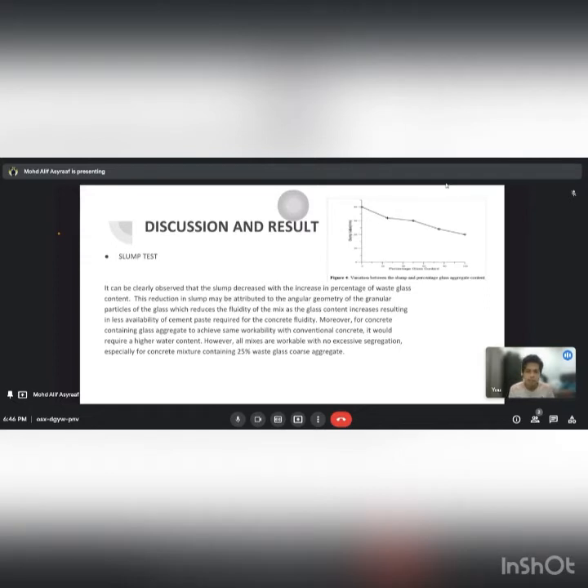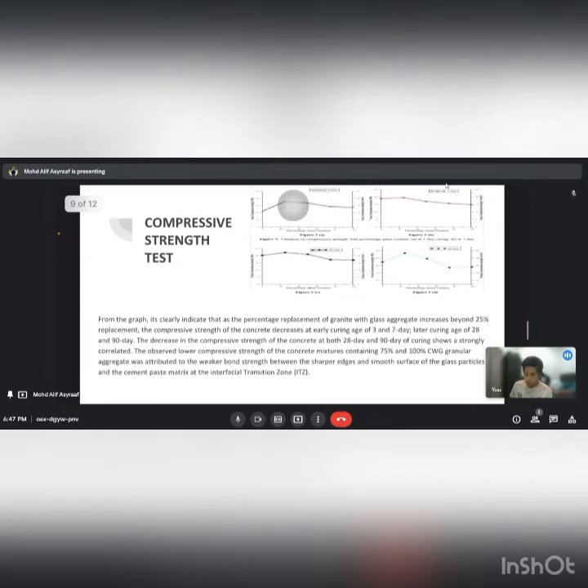So for the discussion and the results, for the slump test, it can be clearly observed that the slump decreased with the increase in the percentage of waste glass, as in the graph above. This reduction in slump may be attributed to the angular geometry of the granular glass particles, which reduces the fluidity of the mix as the glass content increases, resulting in less cement paste available for the concrete fluidity. Moreover, for concrete containing glass aggregate to achieve the same workability as conventional concrete, it will require higher water content. However, all mixes are workable with no excessive segregation, especially the concrete mixture containing 25% glass coarse aggregate.